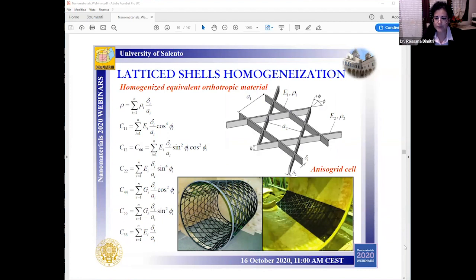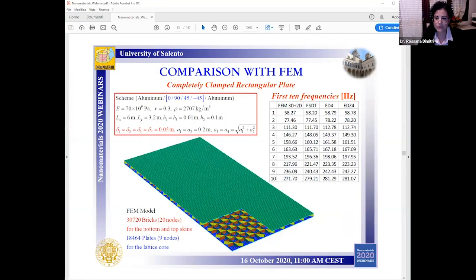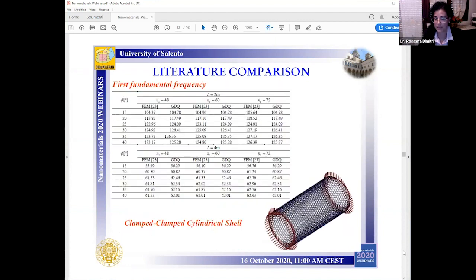So the accuracy of a GDQ-based continuous model is first checked for a completely clamped rectangular plate with a lattice core by comparing our results in terms of vibration frequencies with respect to a classical FEM approach. So the very good agreement between our results and those ones based on the FEM approach confirms the good performance and accuracy of the proposed numerical method, also for this kind of application.